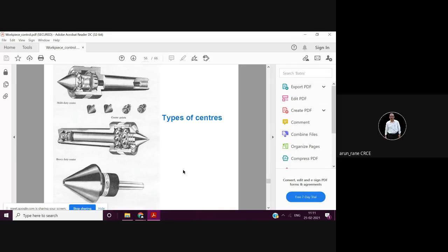So if the circumference is out of round by 0.1, let us say, normally 0.1, 0.2 की ovality हो जाती है. Now imagine the collets are ground and perfect within 0.02, and your workpiece is out of round by 0.2, isn't it? So at some places it will hold, some places it will not hold. सर, तो ऐसा बोल सकते हैं वो टोटल आउट ऑफ राउंड 0.4 के स्केल में होगा? हाँ, if you control the scaling within 0.04, then you can get a grip.